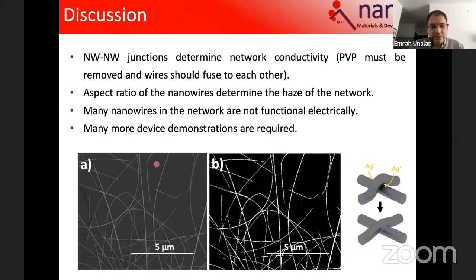And the other thing is that we spray coat these nanowires onto substrates. And as you see, you only create a conducting path, and most of them are not functional electrically, plus optically they are blocking the light. So you need to remove them by some means. So that is another problem that needs to be taken care of.